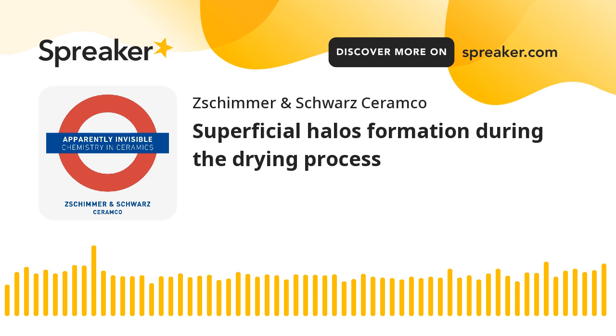Speaking about mechanical resistance, we know that to increase the resistance of a raw tile it is necessary to remove the water from the system by means of a proper drying cycle that, thanks to the evaporation process, gradually excludes the water from the tile. We could also say more specifically that the water molecules, thanks to the drying process, must progressively move from the center of the ceramic body towards the outer layers, evaporating and so allowing the system to bind, and therefore minimizing possible stress. In any case, the drying process must follow precise procedures to avoid critical issues that may arise in the following steps of the production process.